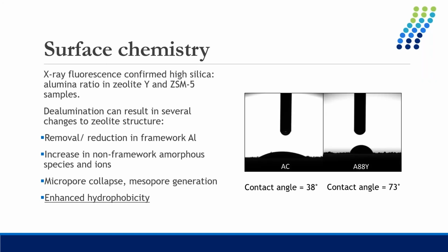And we can see that this hydrophobicity, at least surface hydrophobicity, has been increased in the zeolite Y sample, since it was the only zeolite found to actually present some sort of water contact angle, in this case around 73 degrees. And the other hydrophobic material, activated charcoal, also had a contact angle. Although these are fairly low and aren't really considered hydrophobic by any means, they are at least higher than the other materials we tested, in which water was found to wet the surface immediately.